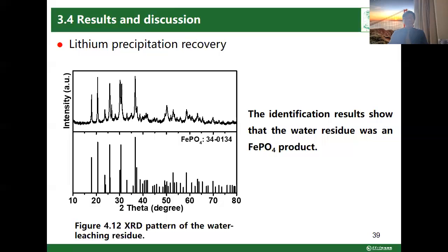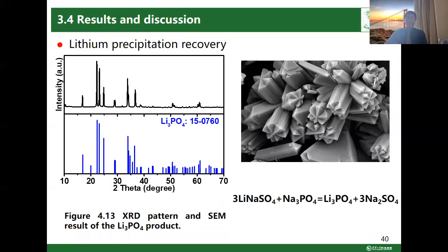This figure is the XRD pattern of the water leaching residue. The identification results show the composition of the water leaching residue. With this chemical as a precipitant, the lithium in this solution can be recovered by chemical precipitation to finally obtain the compound. The reaction equation is given here. The result in this figure shows that the resulting product is indeed what we want. Further analysis through SEM also shows that we get the right compound.